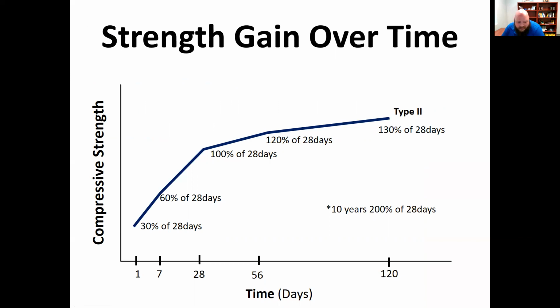You may see at 1 day or 3 days something like 30% of the 28-day strength. And then at things like 7 days, you may see something like 60% of your 28-day number. And then obviously, if you're at 56 days, you may be at 100 to 120% of your 28-day number.